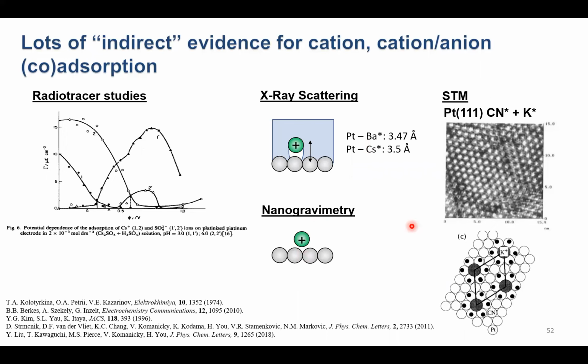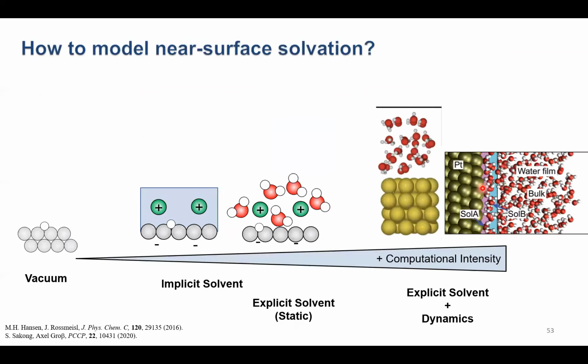And I think what to me is maybe one of the coolest experiments is we can look at STM imaging of a cyanide add layer on platinum 111. Cyanide binds very strongly to platinum, forms a well-ordered add layer. And it also interacts very strongly with potassium in solution, such that potassium specifically adsorbs, and these bright spots actually correspond to potassium on the surface in the cyanide add layer that we're seeing with the STM. And the only way we would see the cation in the STM would be if it's bound so strongly to the cyanide or to the surface that it's not rapidly diffusing around, which would just show up as noise in the STM.